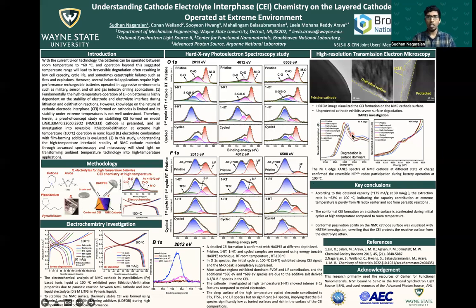After this chemical understanding, we wanted to visualize the cathode electrolyte interface, and as you can see, we investigated with HRTEM analysis. The pristine cathode is free from surface layers. With the pure ionic liquid without any additives, the cathode was cycled at high temperature, and that cathode was degraded, and as you can see, the surface was severely degraded. But after protection, the nanoscale interface layer is here, that is protecting the surface from electrolyte attack.